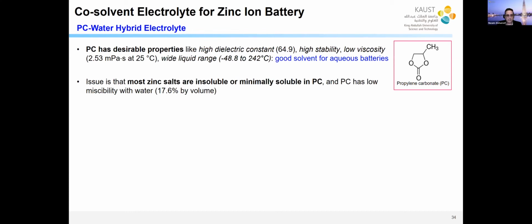The problem is that none of the zinc salts dissolve in this material. So we have a lot of zinc salts. To make an electrolyte, you need the solvent, you need the salt, and maybe you need additives. So the zinc salts don't dissolve in this material. And even worse, this material does not have good miscibility with water. You can only add about 17% by volume. After that, you get phase separation. So we were trying to engineer the electrolyte to see if we can use this material because it will allow us some desirable features.